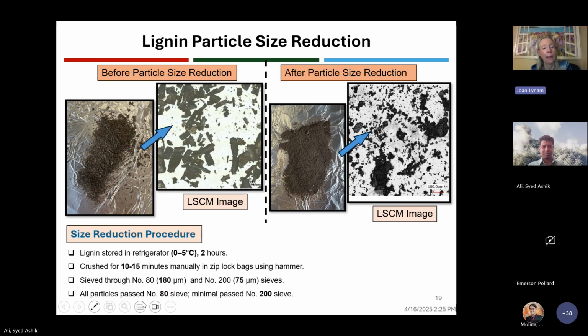So it was all smaller than 180 microns, but most of it was bigger than 75 microns. So we kind of had a small particle size. And those are the laser scanning confocal microscopy images. So you can see that they're at the same scale, so you can see that the particle size went down. That's pretty much the story with that. We can go on to the next one.